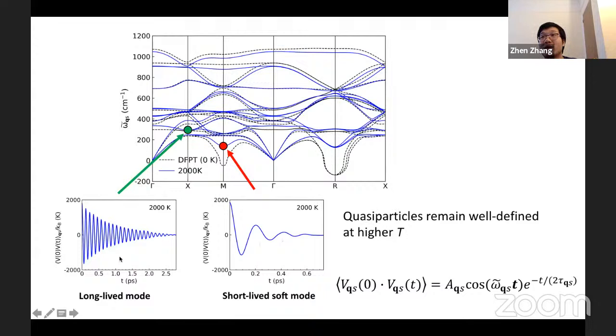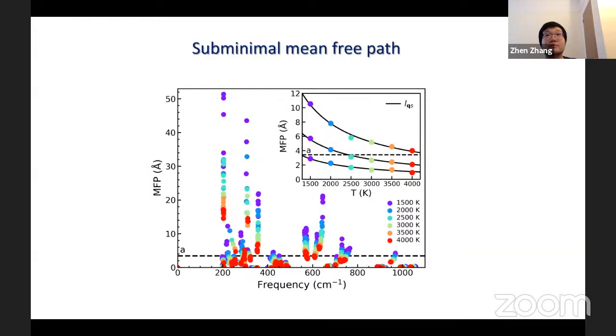For such well-defined single phonon spectrum, distinguishable from other phonon modes, the linearized Boltzmann transport equation can be used to calculate the lattice thermal conductivity. The phonon mean-free path can be obtained by multiplying the velocity and the lifetime. We once again observe the sub-Ioffe-Regel mean-free path at high temperatures, smaller than the cubic lattice parameter a. Here are the collected data for all phonon modes at different temperatures. I choose 3 phonon modes and show their mean-free path as a function of temperature. In the temperature range shown here, one mean-free path remains longer than a, one remains shorter than a, and the other crosses the lattice parameter. No saturation behavior was observed, and the phonon mean-free path roughly obeys the 1/T law.